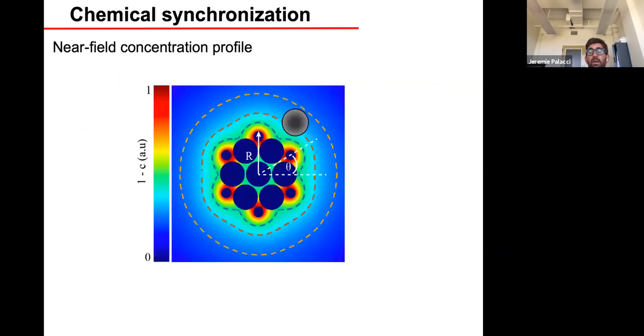So if it's not hydrodynamics, what is it? It has to do with a chemical cloud formed by each particle. Here we have a COMSOL simulation of a rotor: what does the concentration profile look like around a rotor? Here we solve the concentration profile in the static case, so it's Laplacian of C equals 0. The reason we can do that is that the diffusion of the chemical is so much faster than the dynamics, whether rotational dynamics or self-propulsion of particles, that in the reference frame of the particle, the concentration profile is basically steady.